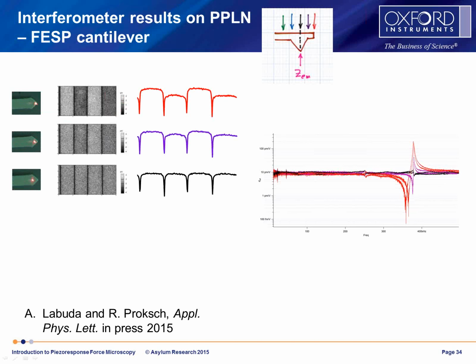Now this is a pretty magical spot, right at this position centered. The domain structure looks equal. The amplitude is equal over the domains. The frequency response over a very wide range of frequency is nearly constant. It comes in at about 9 picometers per volt for this PPLN sample, and except for a couple little hiccups that have to do with maybe not positioning it perfectly over the tip, it's almost a constant function of frequency.